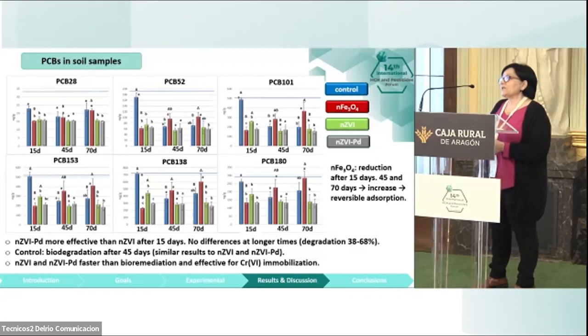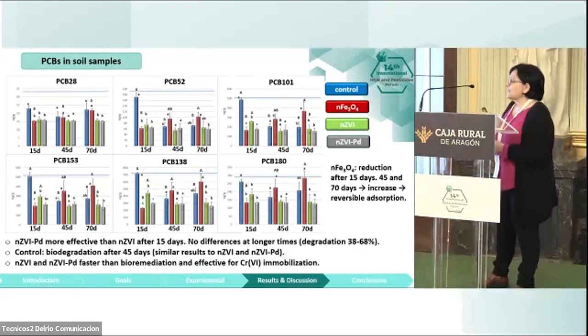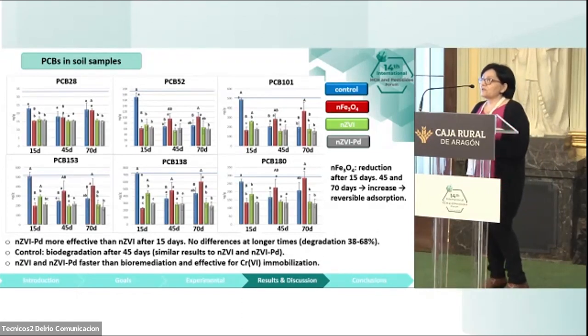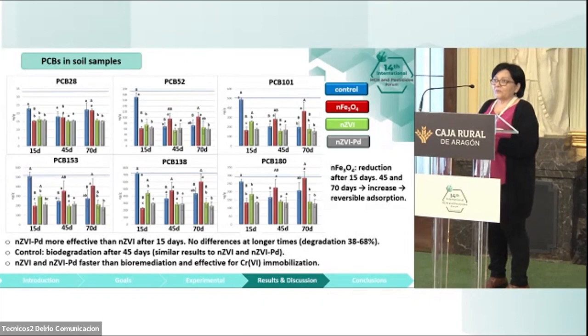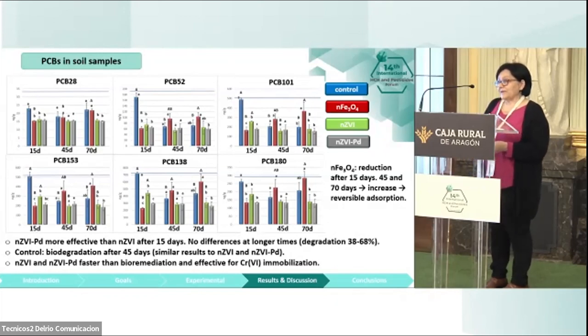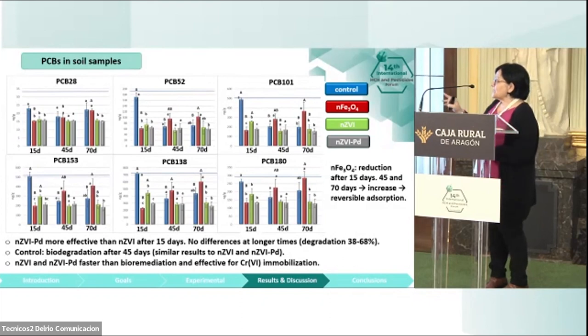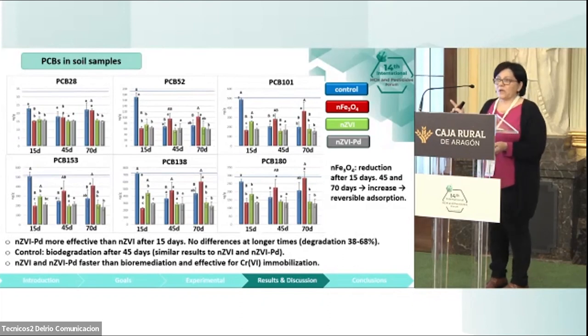This is due, of course, to biodegradation, because we are talking about humid soils, and the microorganisms, with pseudo-anaerobic conditions, are able to degrade the PCBs. So there is a degradation, and over 45 and 70 days in most of the cases, the concentration is the same as with the treatment with nanoparticles. So if there were only PCBs in the soil, then bioremediation would be the appropriate technique. It is also true that the performance is not very high.